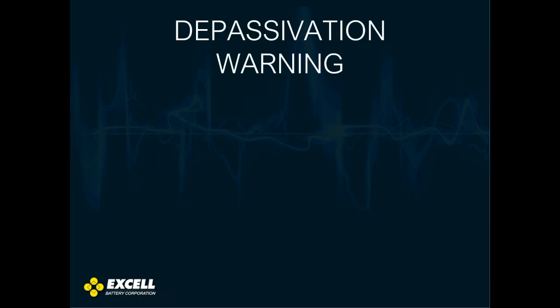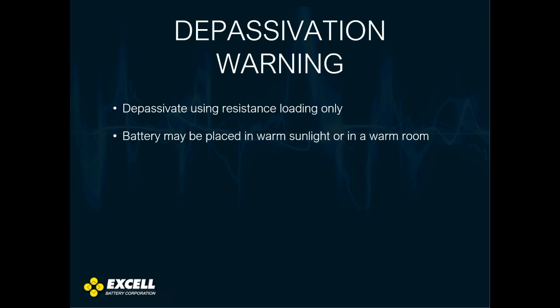We need to give you a warning: you should only depassivate using resistance loading only. You can warm up the battery a little by placing it in a warm room or sunlight, as that will help. But never, never expose a battery to any heat source other than ambient heat. Heat sources like ovens or electrical heat tape can fail and could potentially cause the battery to overheat, which would result in an explosion — that could be very catastrophic. Never use heat to depassivate a battery.